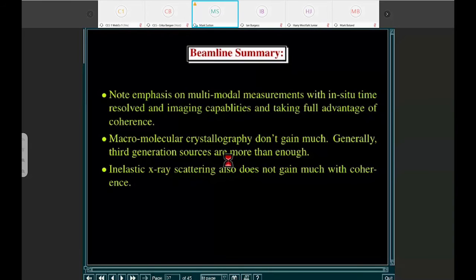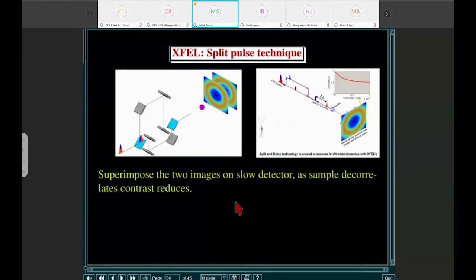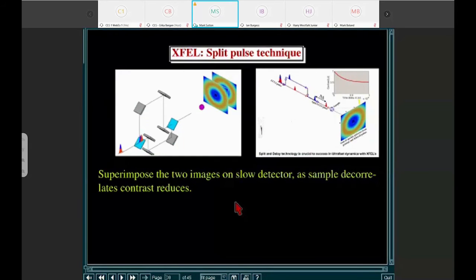With the new free electron lasers, the issue is how can we do XPCS? The typical X-ray free electron lasers only give you an X-ray pulse. It's a very short X-ray pulse, 50 to 100 femtoseconds long, only every few tens of milliseconds, like at 100 hertz. So if you just correlated from pulse to pulse, you would get time constants of order milliseconds or tens of milliseconds, which you can also already do at synchrotrons with most of the setups that are there. How can we take advantage of the short pulse structure of the FEL?